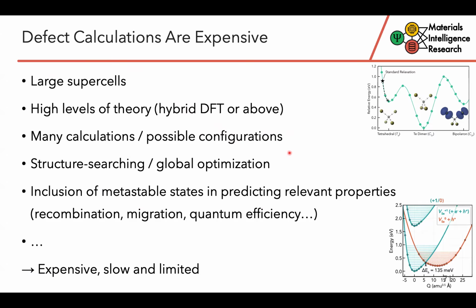Often we have many different calculations to perform, as you might have multiple different possible configurations, particularly in low symmetry systems that need to be investigated. We saw how structure searching can be important. So, as I say, when we use these coarse numerical parameters for our relaxations, it does significantly reduce this cost. So it's maybe like 10 to 20%, I would say, the cost of the full defect investigation. And then we've also seen that including metastable states and downstream predictions, so things like recombination and migration processes, is also important. And so combined, this means that defect investigations are often expensive, slow, and limited.